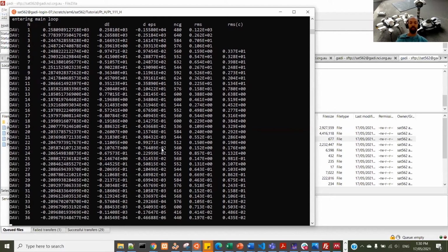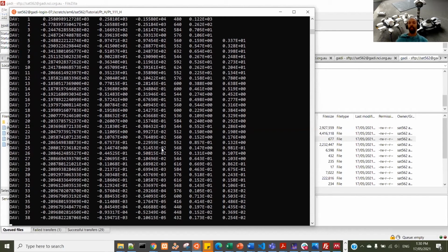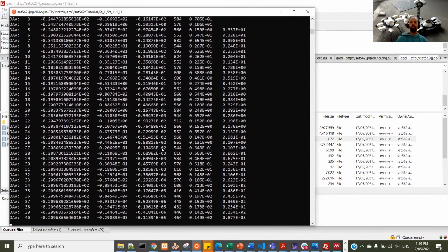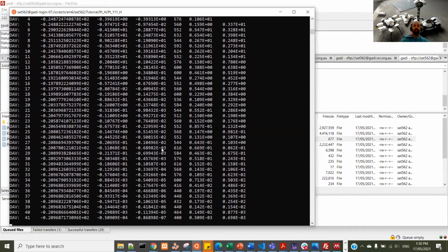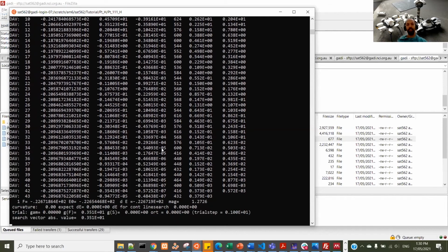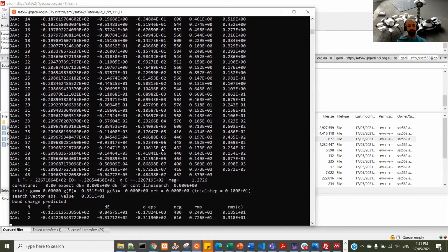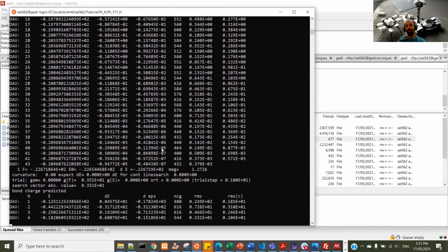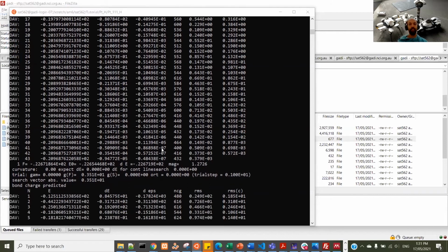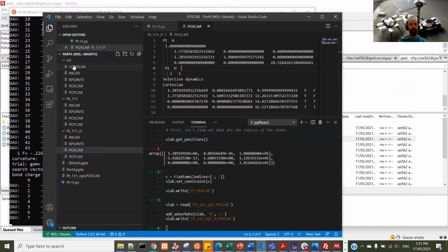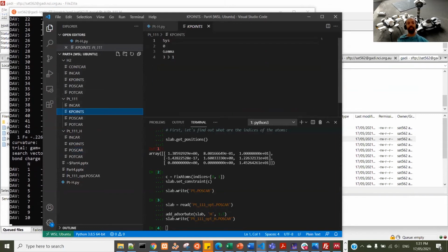And the result is going to be a number that's close to 0.5. Because in this particular situation, I'm only using a system that's very simplistic. So the K points, for example, that I used here, let me just walk you through the parameters. The K points for the slab is 3 by 3 by 1. And that is manifestly an extremely small K-point space for a metallic system.